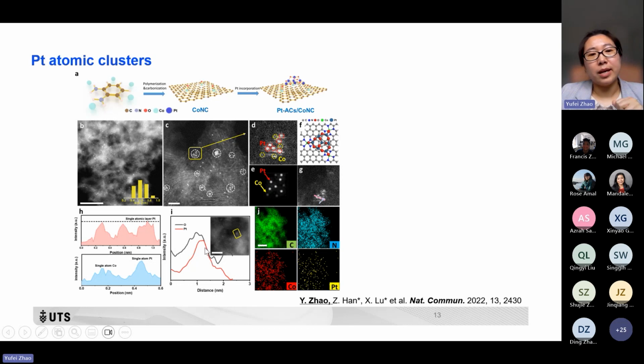And then we have done the EDS line scan for one single atomic cluster. We can see a similar trend of the platinum and oxygen. That means this atomic cluster may not be a metallic atomic cluster, but the oxygen here links these platinum atoms together to form a slightly oxidized cluster for the HER.